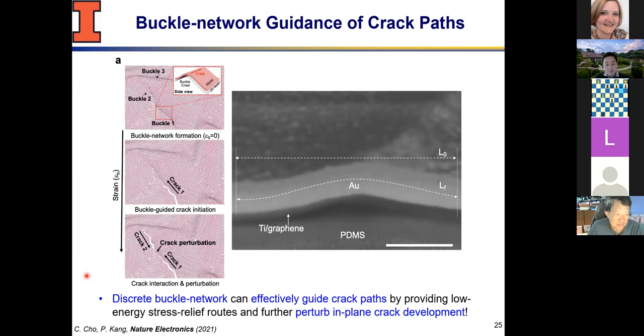So here is our hypothesis, or what we think is the mechanism. It's interesting how this ties back to the wrinkle or the buckle in this case. Our thought here is that having the graphene underneath, in between the gold or titanium gold and the PDMS, because of the different adhesion between just the metal with PDMS versus the graphene with PDMS, you start to create, in our microscopy evidence, these local buckles. They're localized delaminated buckles, as you're seeing here. So we basically modeled a schematic that shows these out of plane localized deformations.